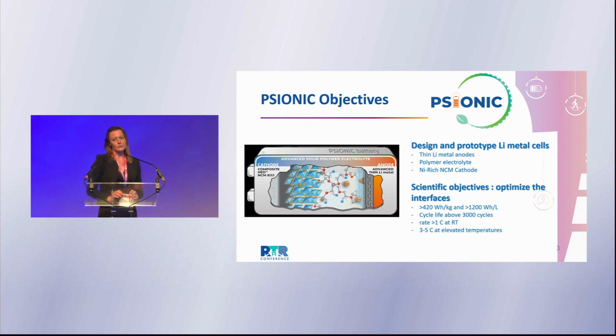Of course, we want to reach also very high cycling lives in order to tackle different applications, not only EVs, but also commercial vehicles, etc. So our target is around 3,000 cycles. And of course, for EVs, you all know that we will need fast charging, so we need to improve all the performances and the power capabilities of our cells to reach 3 to 5 C performance at elevated temperature. I mean, with that we will not do fast charging at minus 20 degrees, of course, but at least between 25 and 40 degrees, we want to be able to fast charge.